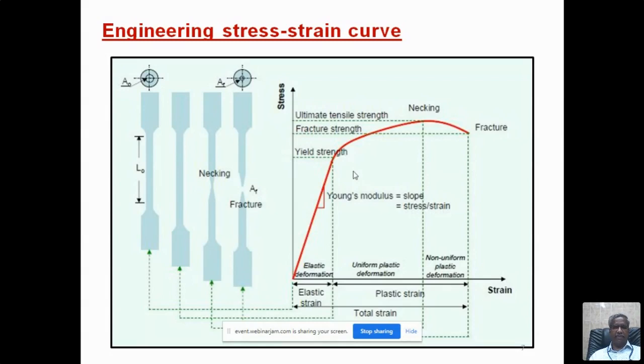Suppose you are marking 50 mm as the gauge length, or 100 mm as the gauge length. So the gauge length you can fix based on the length of the specimen, and the length of the specimen you can decide based on the machine capability. Some machines require 300 mm length. Conventional UTMs, universal testing machines, hydraulic machines or screw-driven machines, require longer specimens. But in recent times, even tabletop UTM machines have come. Those machines can take even small specimens, even 50 mm length.